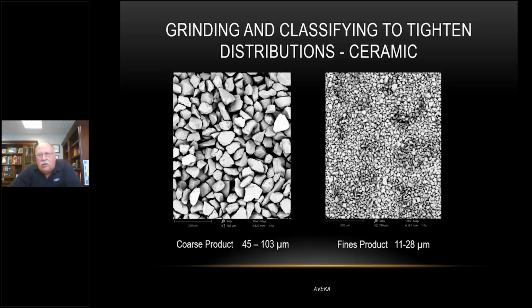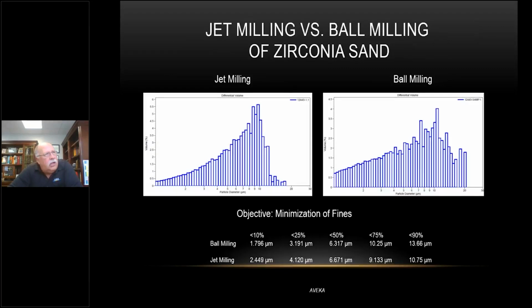Now let's take a look at something where we're just going to look at jet milling and compare it to a different technique, ball milling. So what we're doing here is we're grinding zirconia sand. So this is a rather big particle to start with. And what we're looking at is what happens with a jet milling process or a ball milling process. Now, if you look at the bottom of the screen here, you see that the D50 is about the same size, 6.3 to 6.6.